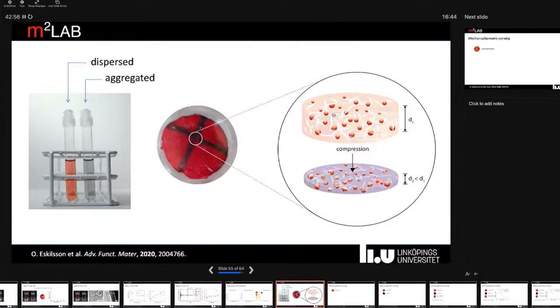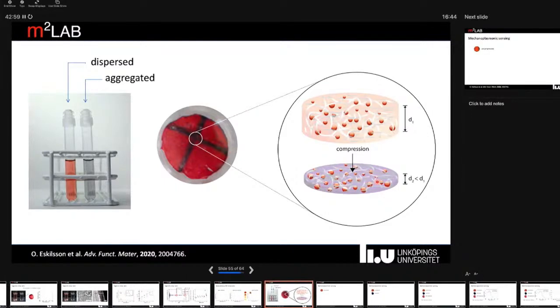But something that really caught our attention was what happened when we subjected these composite materials to a bit of mechanical pressure. Then we saw that we got a change in color, similar to what we see when we aggregate particles. But when we looked at this in the electron microscope, the particles were still fairly well separated. There was no difference here. So this is essentially just an effect of pressing or compressing the material and making the particles immobilized on individual fibrils come close enough for us to get plasmonic coupling.